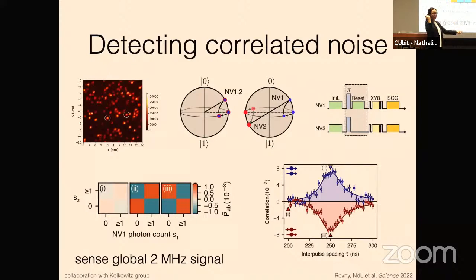And then because these are spins, we can just do this trick where we also prepare them on opposite sides of the Bloch sphere and do the exact same experiment. And what you should see is an anti-correlation. And you see that this checkerboard pattern nicely just flips. So what we've done here is just applied some 2 megahertz signal, and we can put in this XY8 pulse where we sweep the time delay to become maximally sensitive to this 2 megahertz signal or minimally sensitive. And you see that we can nicely resolve this feature in frequency space, and that we see a perfect mirror symmetry with the anti-correlation, which shows that we're really sensing this magnetic correlation. And the magnitude of this correlation here is basically 1 over the readout noise squared. So it quantitatively matches what we expect.